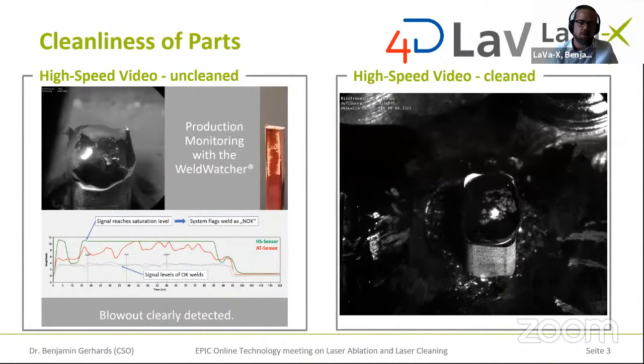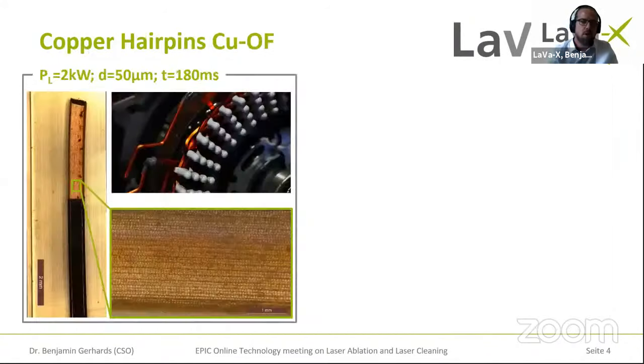And this is also due to the fact that in the vacuum we have low heat conductivity to the atmosphere because it's missing. And therefore the molten pool stays liquid a little bit longer. And pores that are in the molten pool have the ability to gas out of the molten pool. We can use for these welds, when welding, for example, the oxygen-free copper grades, a 2 kilowatt laser with a 50 micron diameter. And we will just need 180 milliseconds for the weld.